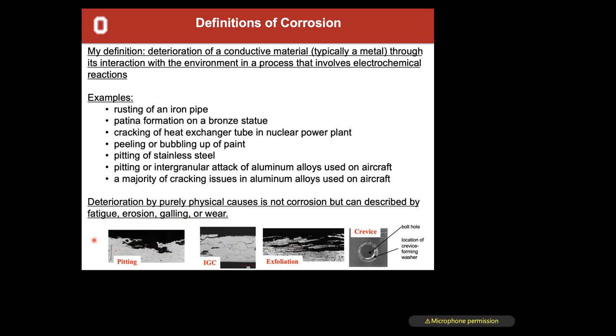We have things like pitting corrosion, where you're just making a pit or a gouge in your surface. Intergranular corrosion, it's very specific sites. We call them grain boundaries. You don't necessarily need to know what that means, but it looks like this, where you have very specific sites of corrosion attack through your material. And this can be very egregious for mechanical properties. Exfoliation is basically intergranular corrosion, but it's in a material where it flakes up, like a severe exfoliation of your skin, like the book pages are opening up. You actually can see this sometimes in near seacoast environments on a lot of materials. So if you look around and you see your material flaking away, it's exfoliation corrosion.